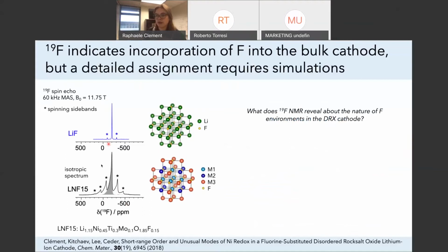So if we just compare these two spectra, what can we say about the integration of fluorine in the DRX structure? Well, we can see clearly that the signal changes from going from LiF to LNF15. LiF is the precursor in the synthesis of these materials. So we do have some intensity at the position of LiF, which suggests that we have some residual LiF in the material, but we also have a wide range of other environments here with different chemical shifts, which suggests that we have successfully incorporated fluorine in the DRX structure.